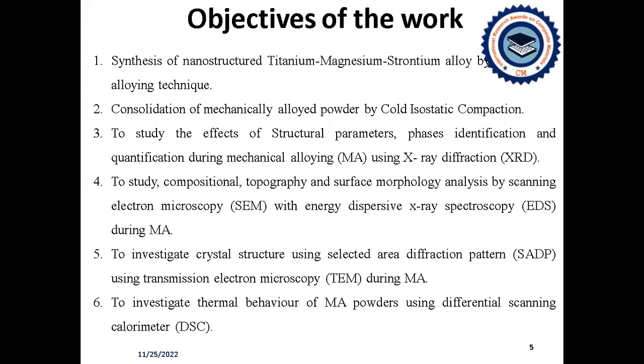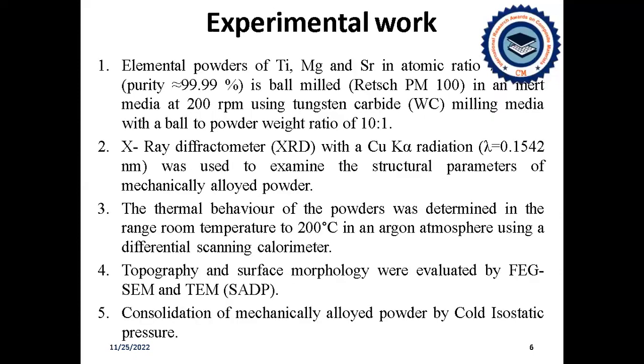Also, in order to find out the crystal structure, that is the structural parameters of the alloyed powder as well as the compact sample, transmission electron microscopy, that is TEM analysis, is carried out. Also, to investigate the thermal behavior of the alloyed powder along with the compact sample, a differential scanning calorimeter was used for the thermal investigation of the alloyed powder as well as the compact sample.